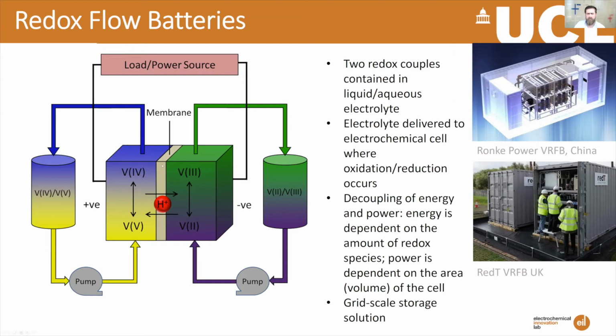So say you've got two redox couples contained in two separate tanks. They flow into a device that does charge transfer, the charging and discharging, and because of that, you're decoupling the energy and the power of the system, so they're really quite flexible. And I should say that most of the time they have quite low energy densities compared to lithium-ion batteries, for example. So we're talking firmly grid-scale energy storage solutions here.